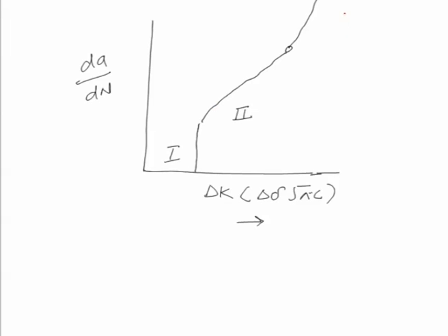So, here for the different metal systems this slope is found at different angles. For those metal systems where the slope is low, the crack growth rate will be slow and the fatigue performance will be better as compared to the material systems which show a higher crack growth rate. So, this is for low crack growth rate and this is for high crack growth rate, and these high crack growth rate materials will show poor performance under fatigue load conditions.